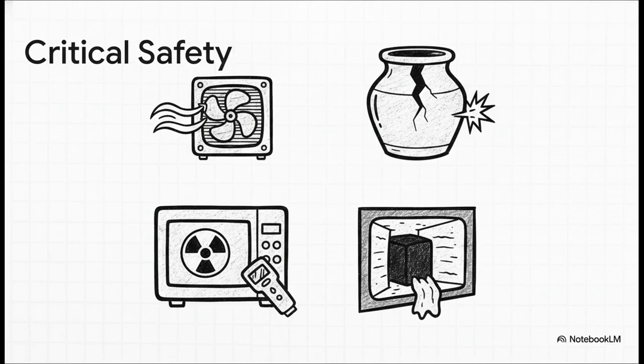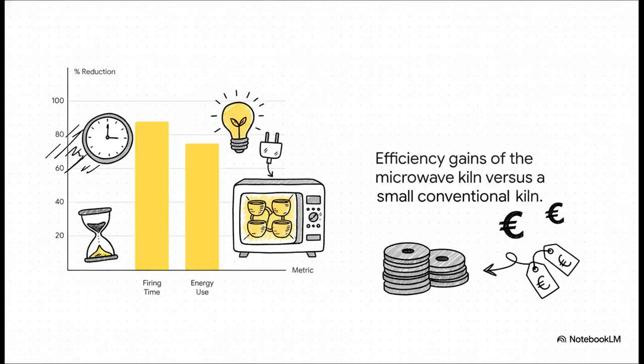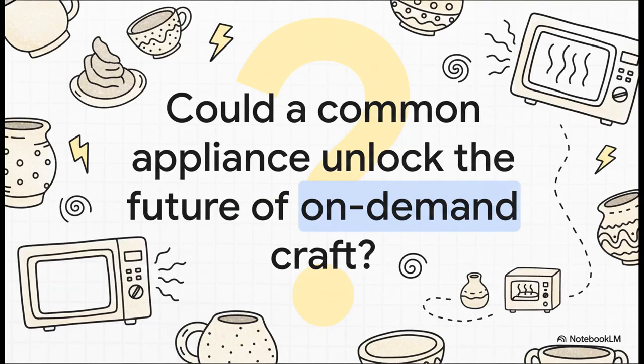The study also found that at super high temps, the iron-rich susceptors could actually react with and melt the insulation if they touched. But you just can't deny the potential here. The time savings are huge. We're talking over 85%. The energy it uses for each piece is right on par with big, efficient industrial kilns, which makes it perfect for the small batches an artist would be making. And the cost to make the most important part, the susceptors, is incredibly low, just 15 to 21 euros for a whole batch. So, this leaves us with a pretty cool final thought.